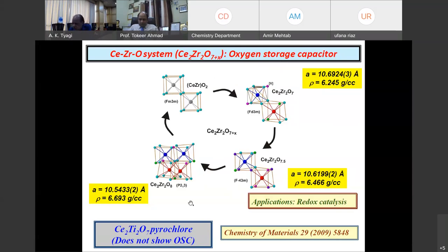Unfortunately, face to face, we are not there. I would have loved to get an answer from you. Why is it that Ce2Zr2O7 pyrochlore shows this kind of reversible transformation and titanium pyrochlore collapses? The reason is the same. Titanium is too small to have the coordination number of the fluorite lattice. Titanium 4+ cannot adopt so easily coordination number 8. Zirconium is comfortable with 6-fold coordination and also with 8-fold coordination. So again, the message is that you have to have the right combination of cations.